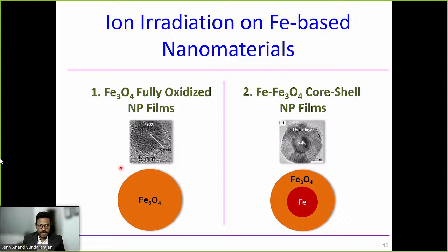One is fully oxidized iron particles, as you see on the left side. The other one is core-shell, which means it has a core of iron and the surface is all oxidized. So we take these two particles, create a thin film of nanoparticle film, and then expose it to radiation and see.